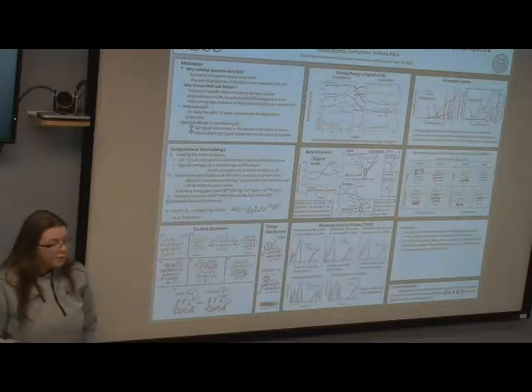So what I'm thinking happens is, when the amine is taken off and there's only one thiol or thiolate on the surface, the binding energy becomes like it's more favorable for the ligand to not be on the surface of the quantum dot and for it to be kind of pushed away into the solvent, or at least not seriously bound.